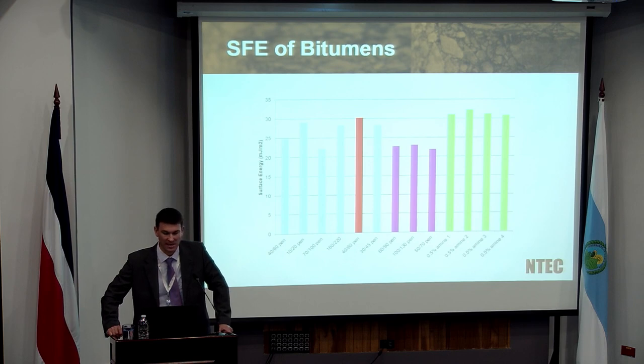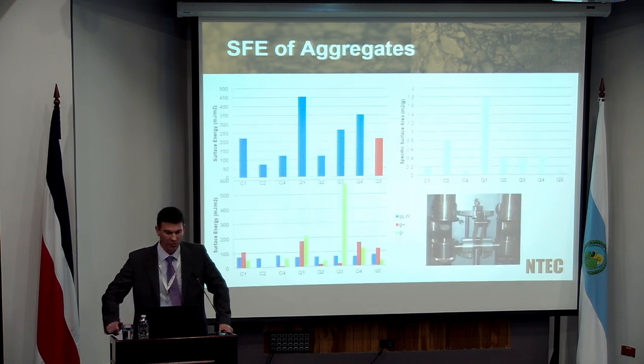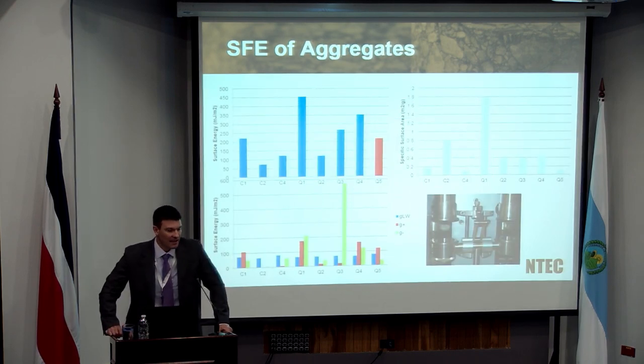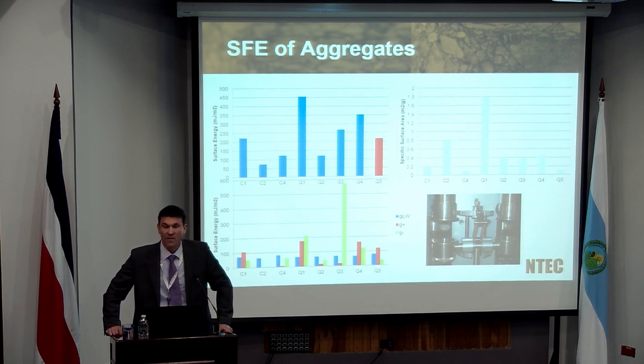And straight away you see that you do see an increase in your surface energy. And obviously the higher your surface energy for a bitumen, the better in terms of its desire to bond with stone or aggregate. So that's the bitumen. What about the aggregate? The first thing to note is the aggregates are very, very different. So whereas bitumen was effectively giving you very similar values for surface energy, didn't seem to make a massive difference in terms of the final calculation in terms of adhesion, if we look at aggregates, they will differ.